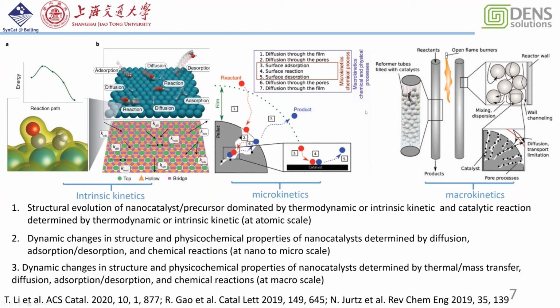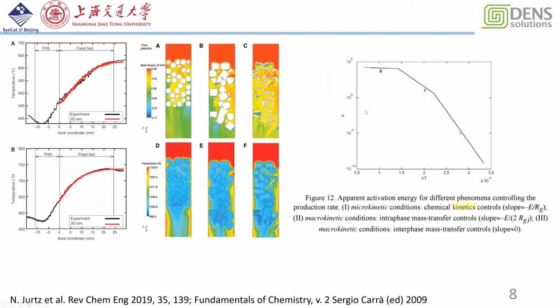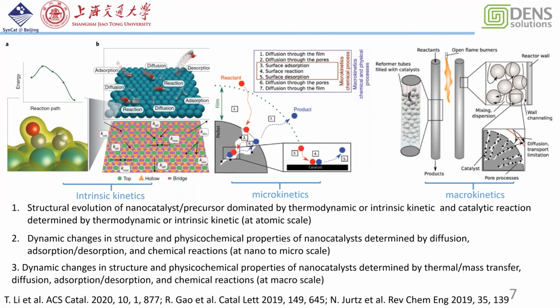Yeah, okay, sorry. So if we separate these three levels of the scientific problem, the thermodynamics will not be changed; even without catalyst, the thermodynamics would be the same. But the kinetics is very different. In the fixed bed reactor, we always call it macrokinetics. And when we focus on a single particle with a size of several nanometers to several hundred nanometers, we call it the intrinsic kinetics. Intrinsic kinetics is often related to the fundamental reaction steps.